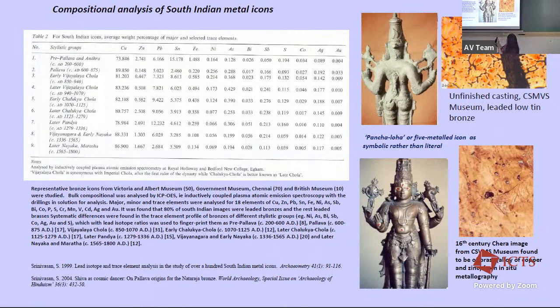And here you can also see the impregnation of the mold material, and you see the lead also in the intergranular spaces. And though, of course, a large number of the Chola pieces were bronzes, as we saw, the tin ranging from less than about, about, say, the average would have been about 6 to 7% tin and 6 to 7% lead and so on. Though, of course, it varies quite a lot, because the major alloying elements can vary quite a lot.